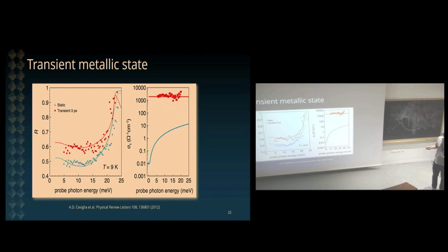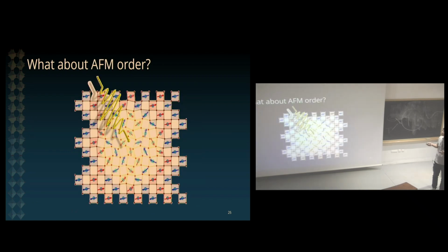And if you do that, you're going to see, for example, by probing with terahertz spectroscopy the conductive properties of this thin film, that at equilibrium you have a well-defined insulating state, and when you excite the lattice of the substrate, the thin film responds very rapidly. Within a picosecond, it becomes metallic. So you have a change of several orders of magnitude in the optical conductivity of the system. So we can really see a transient metallic state by this laser excitation.